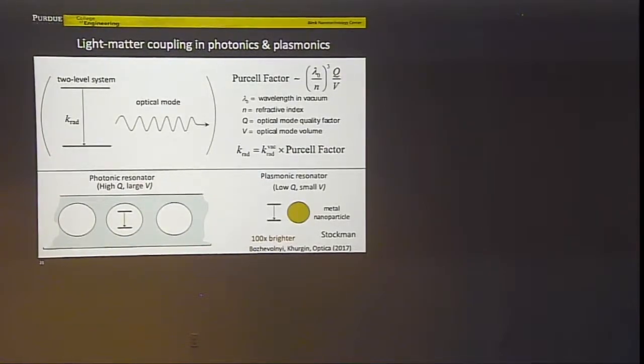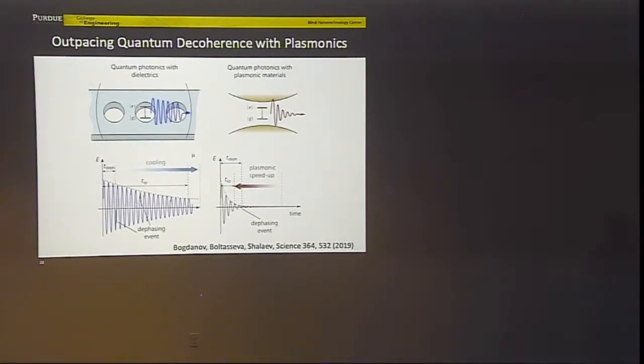That was the idea generated in our group, and actually, as I said, it was just published a few weeks ago in Science. So that's the illustration taken from that paper. The typical approach which all groups pursue is to go to all extremes to increase the coherence time. They trap atoms, they trap ions, they go to low pressure, they go to exceptionally low temperatures, so the decoherence time increases. I'm showing here the example of generating photons. Let's say you would like to generate a single photon, which is one specific process important for quantum information systems. If you would like to have coherent, indistinguishable photons, it means that the coherence time should be longer than the time within which your photon is emitted, so there wouldn't be any change in phase.